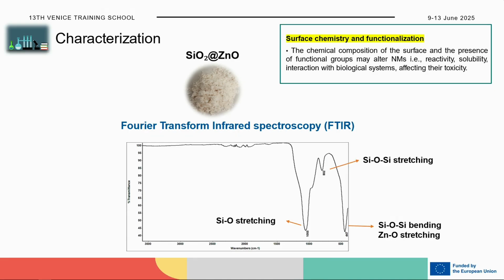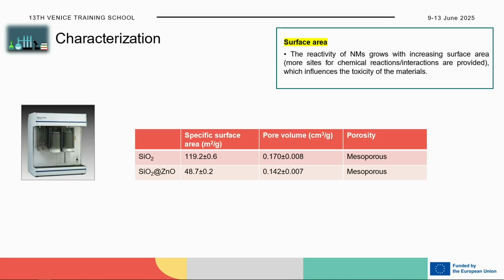Then we look also at the surface chemistry. So we used FTIR spectroscopy and also BET. What we observe in this case by FTIR, we observe the stretching and bending characteristics of the bonds between silicon and oxygen, and also zinc and oxygen. And from the BET, what we observe is that if we compare the specific surface area of the silica dioxide alone and the advanced material, we observe a decrease in the specific surface area. This could occur because we have this kind of layer on the surface that can decrease the surface area because some of the pores of the silica alone were occupied by zinc oxide. Okay.